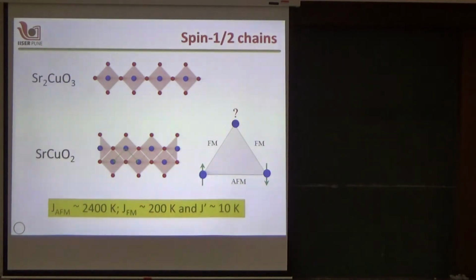That experiment has been done. So even with calcium doping at the strontium site, one sees a gap in the spin excitation, but that happens only for very high concentrations of calcium. You need at least 10% of calcium to see the visible gap. So probably there you are going to the random singlet phase that I talked about in the middle of my talk, the theoretical work by Chandan Das Gupta and Ma.